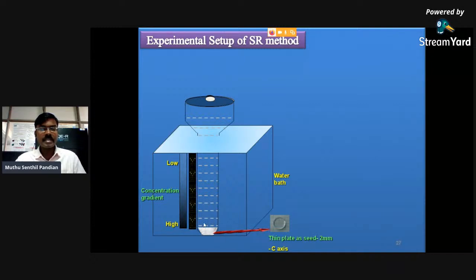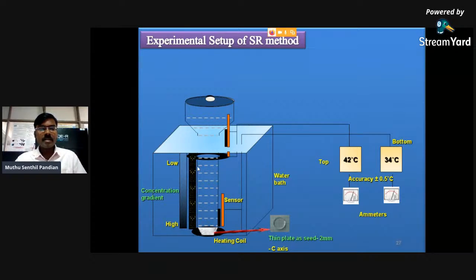So this crystal surface attracts more atoms very easily. The concentration at the bottom portion is very high compared to the top portion. After a few hours, once the solution is stable, we have to apply the two temperatures, one at the top portion and the other at the bottom portion. The top temperature is for solvent evaporation, and the bottom temperature is for growing the crystal. We have to maintain a uniform temperature near the seed crystal, solution and crystal interface for growing the crystal. Otherwise, multinucleation, that is spurious nucleation, will form. Then the growth will be stopped.